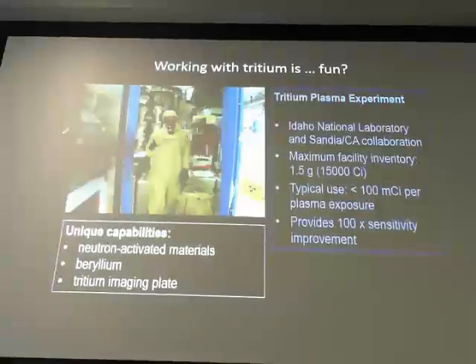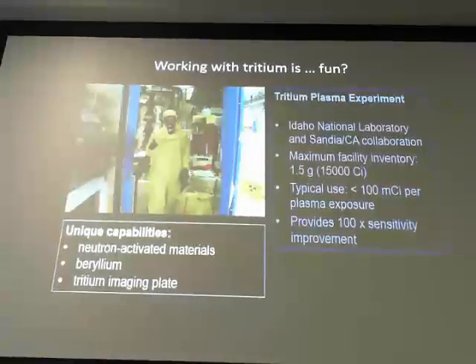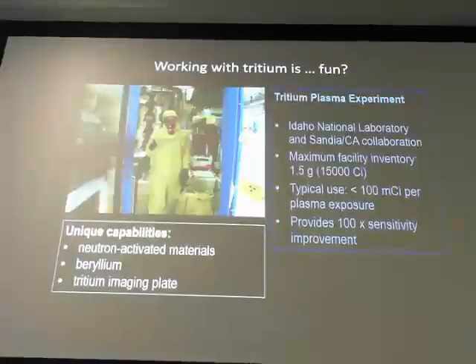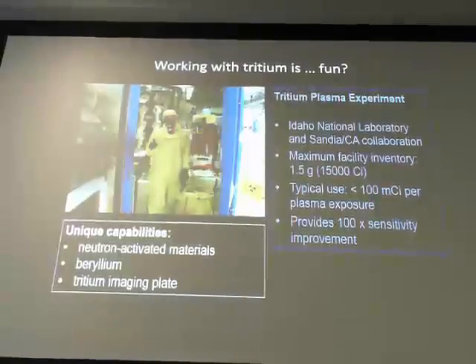The real reason to use tritium is just the fact that it provides higher sensitivity than deuterium would. So it's extremely detectable. If you're doing permeation measurements, plasma-driven permeation measurements, that's going to give you about a factor of 100 better sensitivity than deuterium. And then there's also some specialized effects just due to the tritium. It's a higher mass than protium or deuterium, so as a result, there's some secondary mass effect that might have to be taken into account.